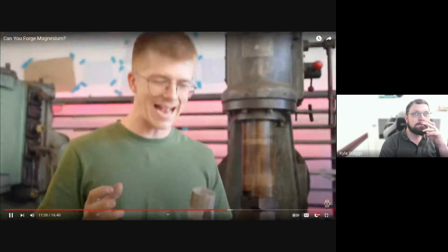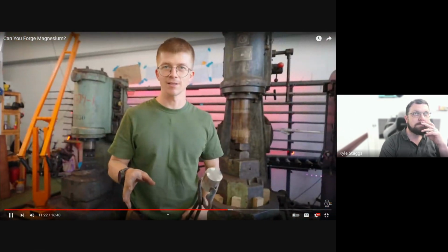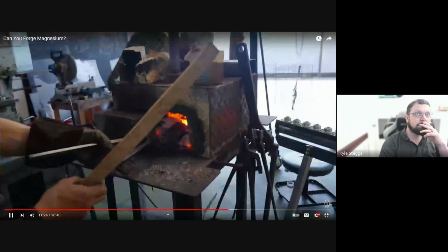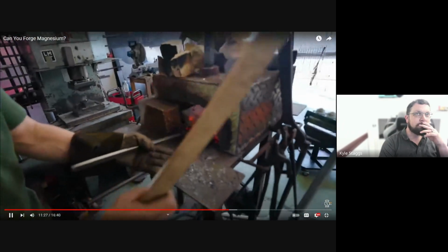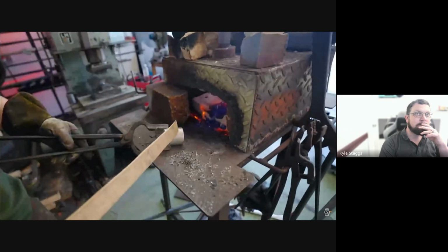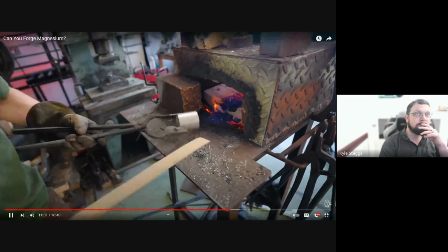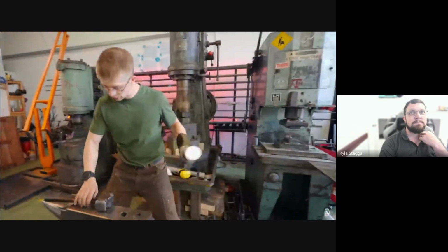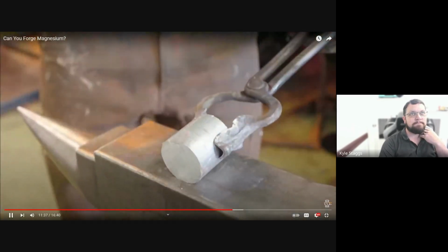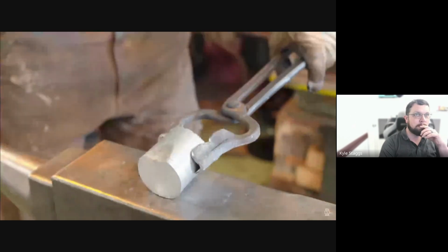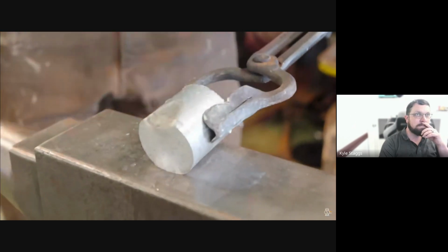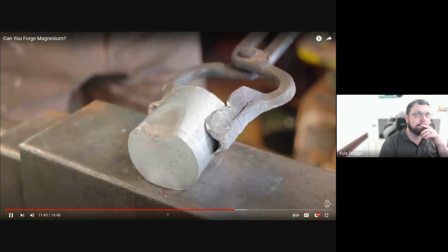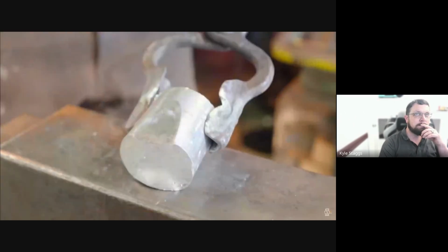I expected this to feel like aluminium. I should show you what aluminium looks like. Here's a trick for working out if aluminium's hot enough to forge. Take a bit of wood, not hot enough to forge. You'll see what I mean when it is. There we go, that tells you it's hot enough to forge when it chars. Forging aluminium is kind of like this. You can hear how it sounds. It just sounds soft. It doesn't bounce around on the anvil and it deforms really, really nicely.